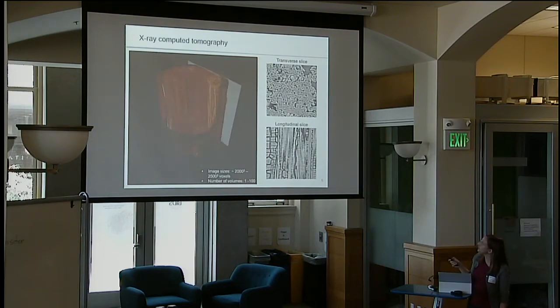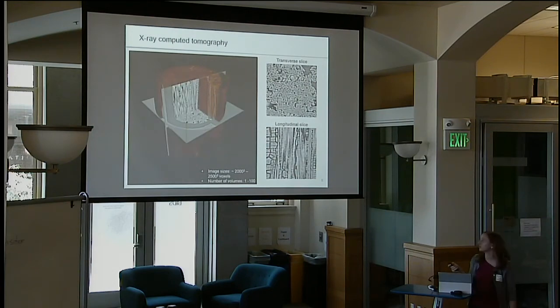The two different views that we look at most commonly, just for simplicity to look at in 2D, are transverse slices, where we see the fibers as circles, and longitudinal slices, where we see them as these long rectangular shapes. And the images are fairly large, 2,000 cubed to 2,500 cubed, and we can collect anywhere from 1 to 100 volumes during a single experiment. So the goal here is to, from these in-situ X-ray computed tomography experiments, really develop the basic science behind how these materials are made.